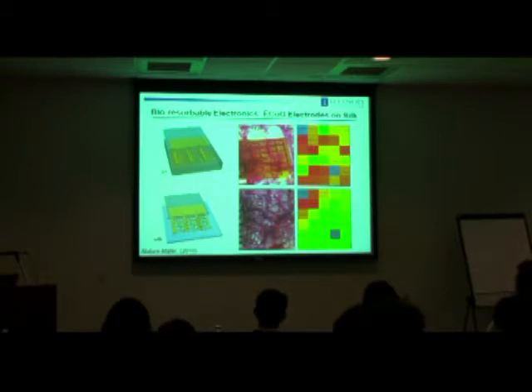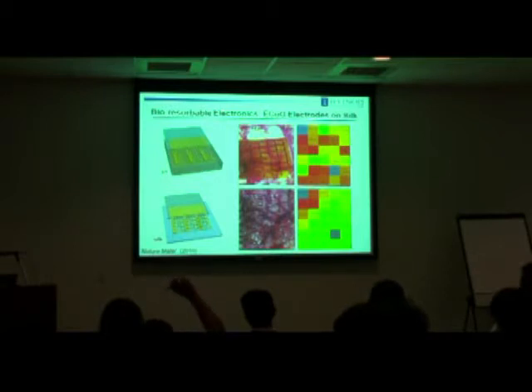This is a cat. So this is a conventional piece of flexible electronics. It does not wrap, as I mentioned before. This is an ultra-thin mesh of electrodes on silk after the silk has been washed away. So you can see this kind of conformal contact, even on this very, very curved, irregular surface of the tissue. And these are actually ECoG signals taken from the brain while the cat is exposed to a different series of images. And the green indicates a likely physiological response, and red is likely noise. So the much better contact yields a much higher fidelity monitoring.